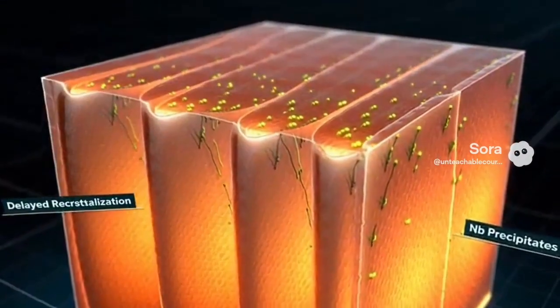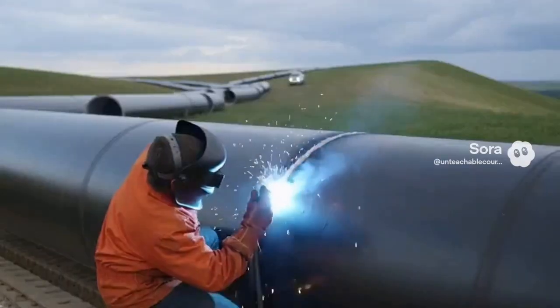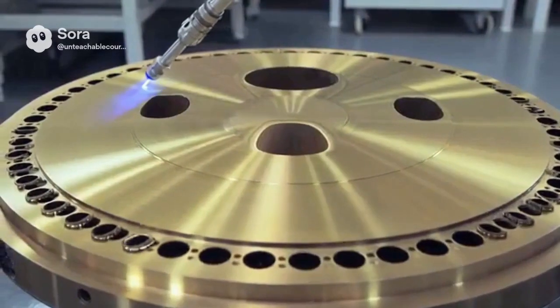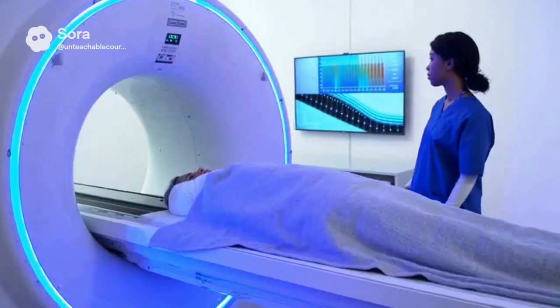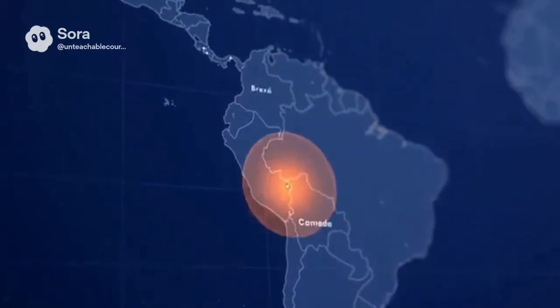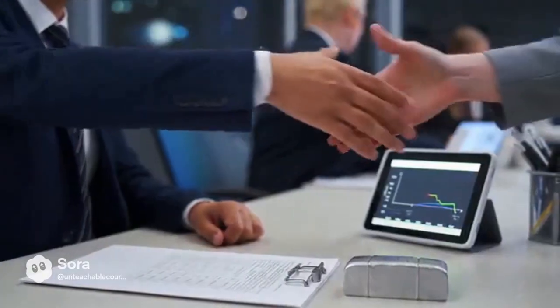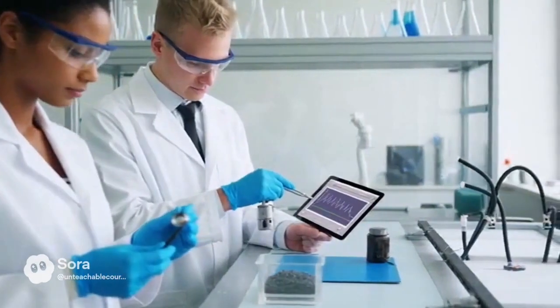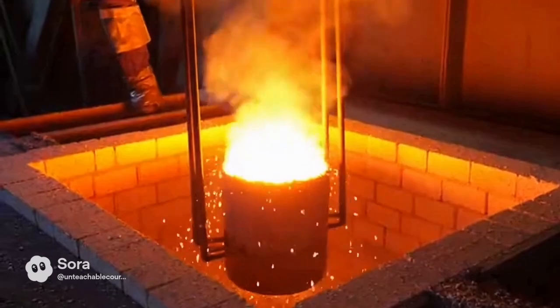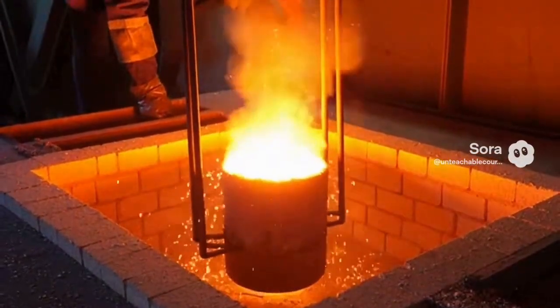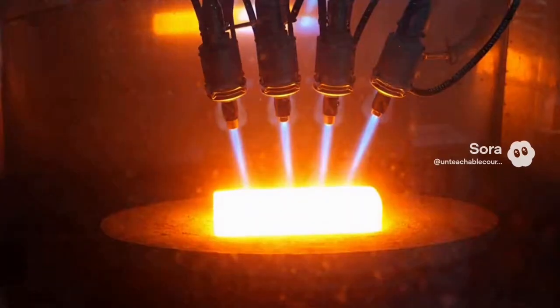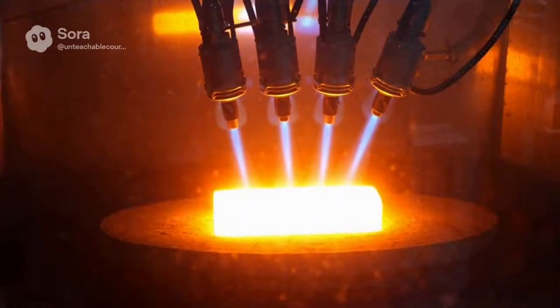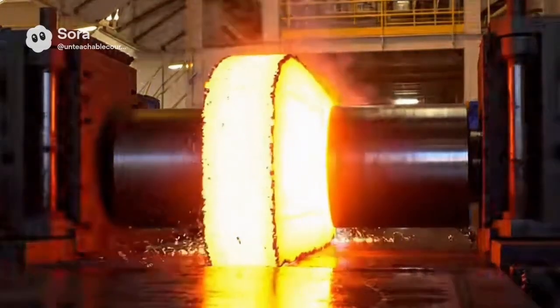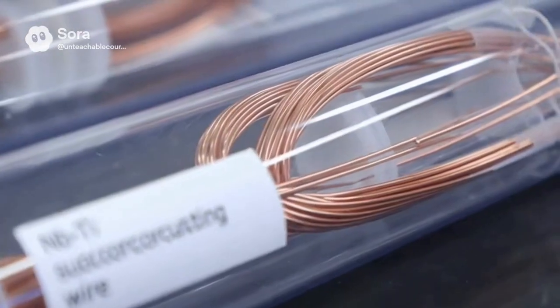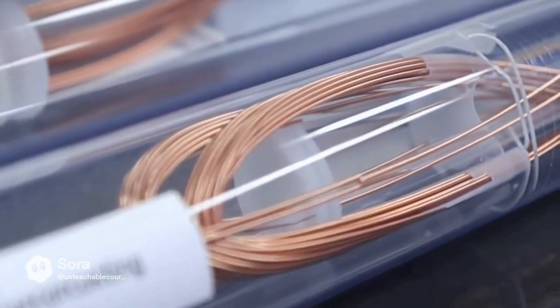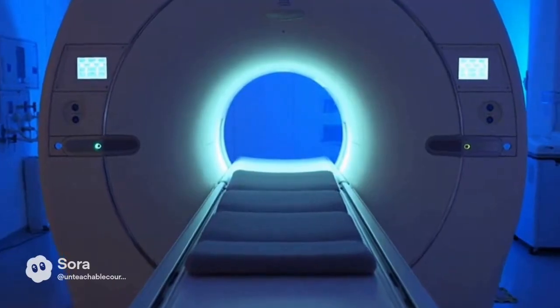The other place substitution appears is in superconductors. The race to higher magnetic fields has drawn in high-temperature superconductors whose critical temperatures and field tolerances outgun niobium tin, at least on paper. In practice, the price, manufacturability, and mechanical quirks of those ceramics keep niobium tin and niobium titanium busy. Hospitals do not rebuild magnet rooms on a whim, accelerator upgrades are grand projects on decade scales. Niobium continues to win not because nobody can beat its physics, but because it lives at the intersection of good enough performance, known manufacturing, and acceptable cost. That is the unglamorous sweet spot where materials earn their keep for decades.